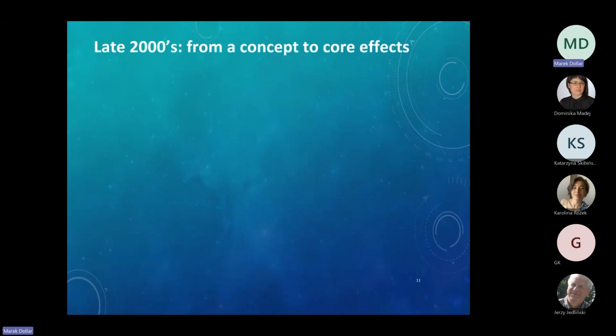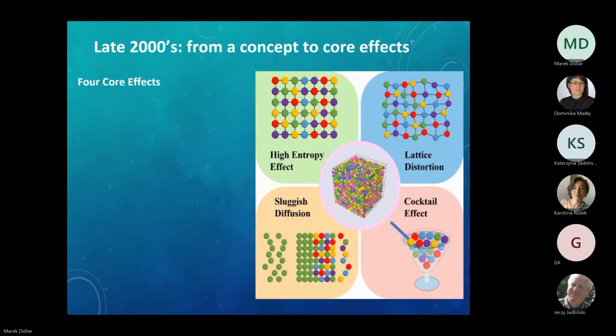Very quickly, around 2010, there was already, and that's fascinating, a pretty good understanding of the four core effects: high entropy effect, lattice distortion, very slow, sluggish diffusion, and what people refer to as the cocktail effect. So a combination of several factors impacting properties.